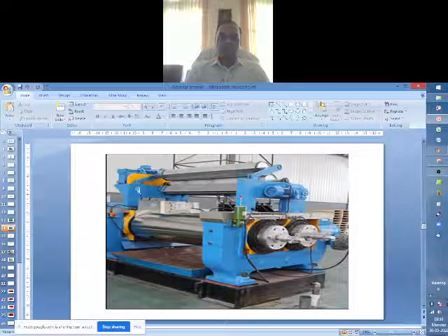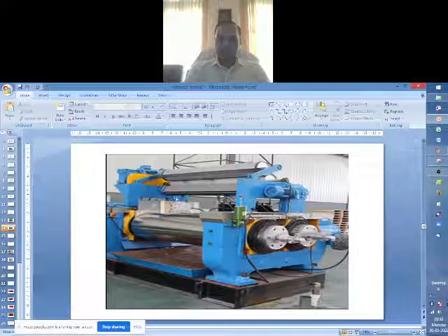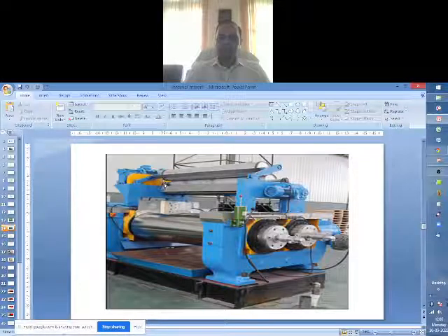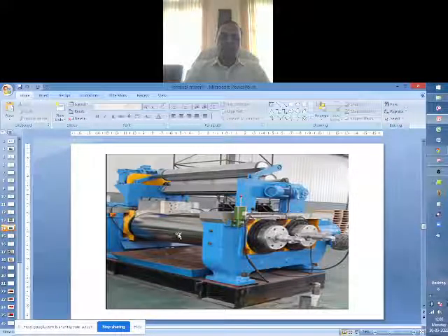From here, if you give a cut and feed it in the top roll, then that will feed in here. And the top roll, the feed coming in where it drops, can be moved from left to right by moving this device here. So you'll have a small band, then that will be draped over this, that will fall back into the system, and then this will move back and forth in a continuous lateral mixing operation. So the manual intervention is minimized and the reproducibility is higher.